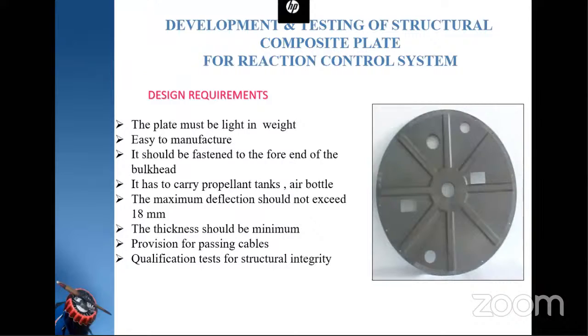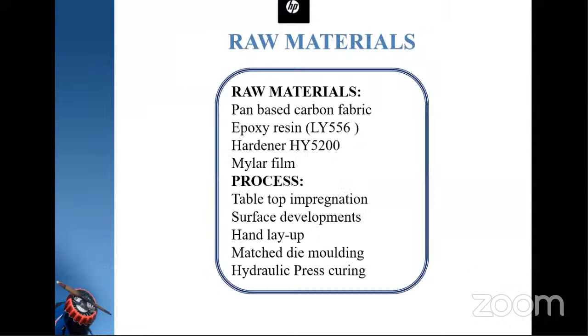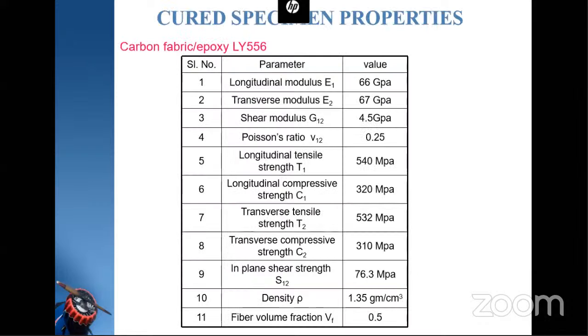This is another component which is made by using a carbon fabric and epoxy resin system, which has to withstand very high load requirements. This component is having ribs on both sides, because in order to avoid deflections, we have designed a plate in such a way that it will have ribs on both sides, and it is made in hydraulic press. So these are the materials used: carbon fabric, epoxy resin. Then the process is hand layup process and matched die molding, hydraulic press curing.